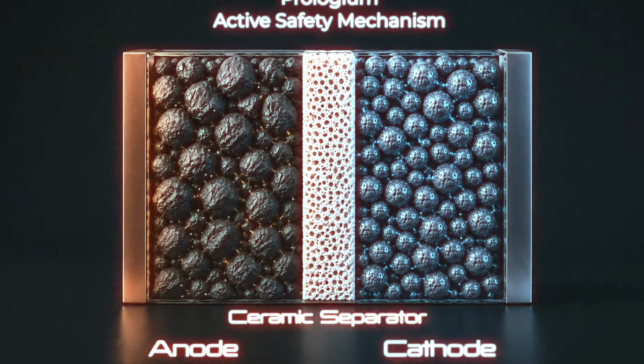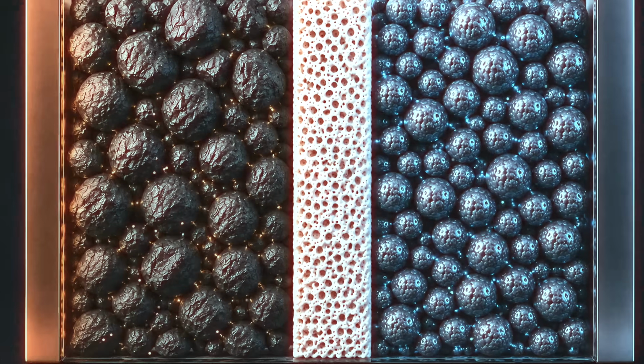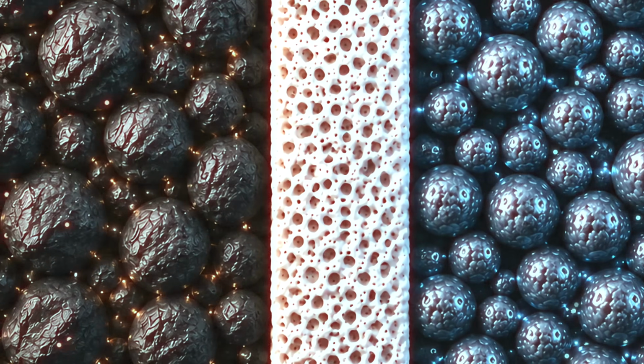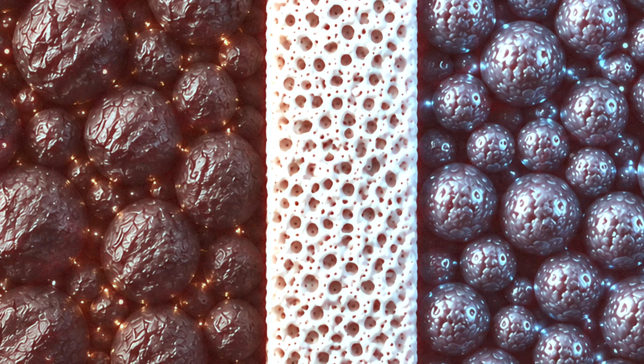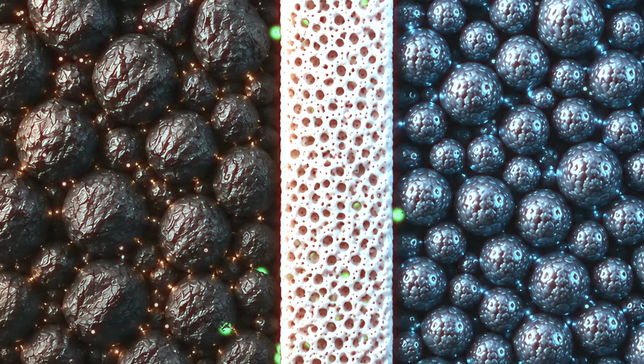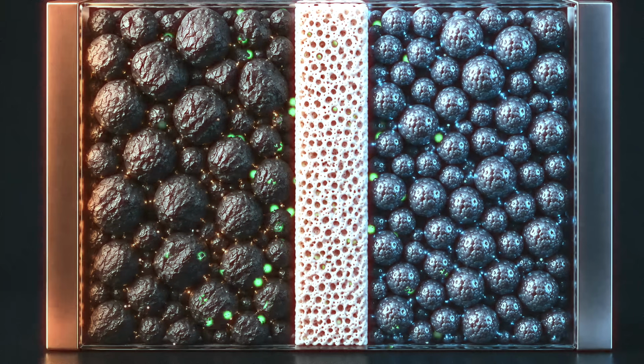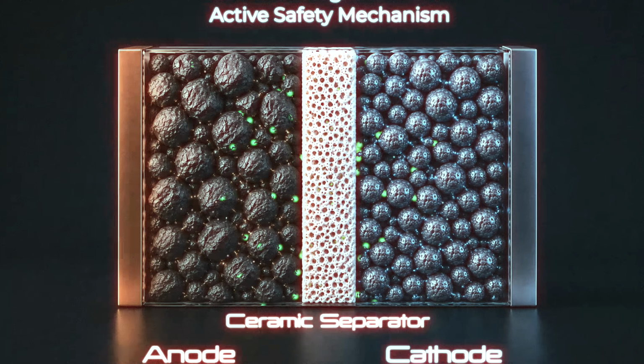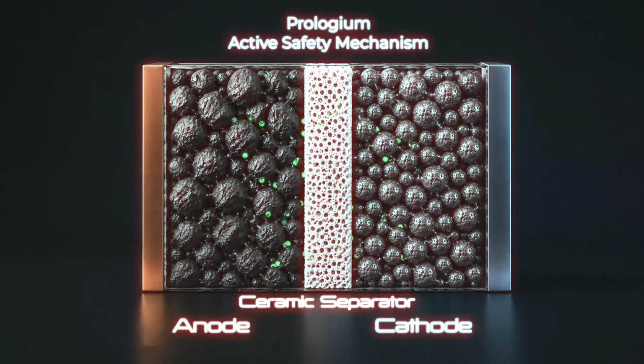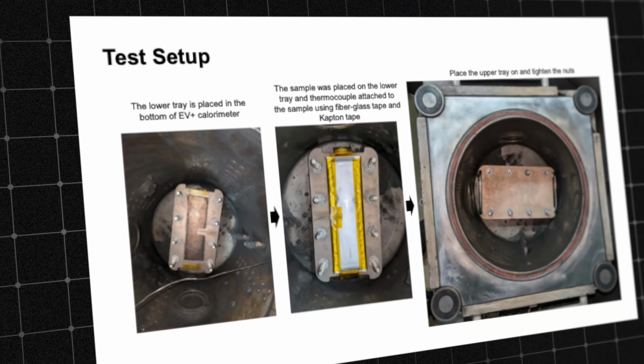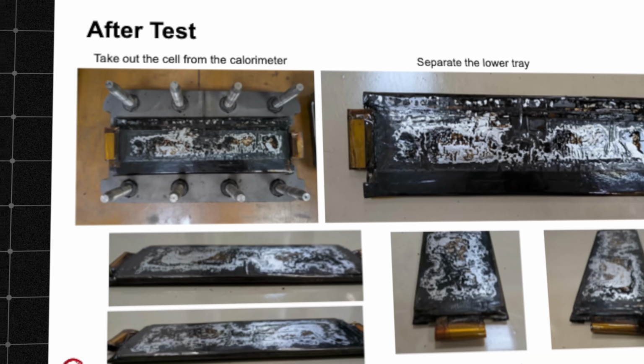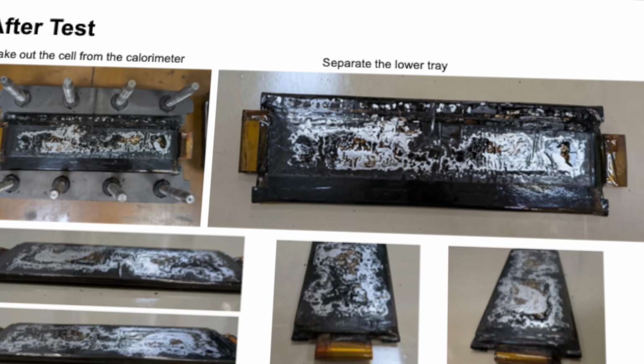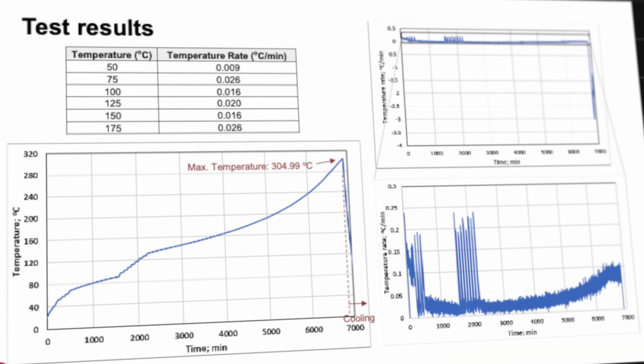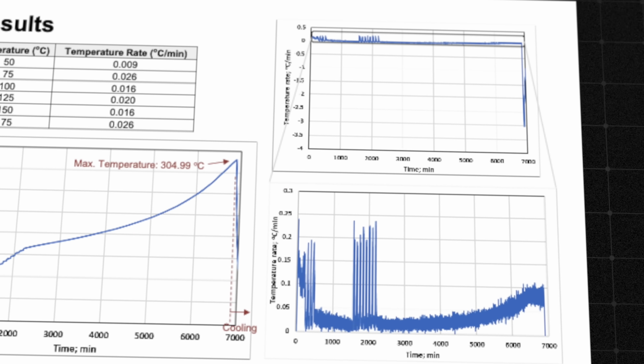Number 3 is ASM, or the active safety mechanism. This part is pretty genius. Built directly into the electrolyte is a chemistry that activates at around 125 degrees Celsius, before a runaway can even start, and chemically dismantles the charged cathode and anode, converting them into low energy compounds. The cell goes permanently dead, and it doesn't burn. It doesn't really even get particularly warm. ProLogium's Gen 4 cell is the first lithium battery in 40 years to pass the gold standard ARC, or accelerating rate calorimetry test, without going into thermal runaway. And the result has been independently third-party tested.